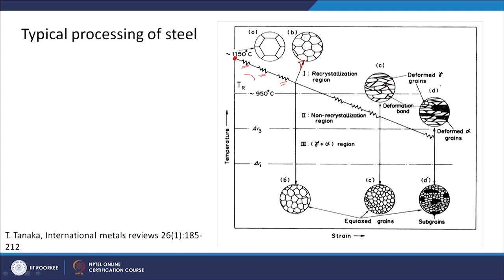deformation. So, deformation in the gamma phase, that means the austenite phase. Again the temperature is continuously dropping and then you are putting deformation here. So, these are deformed alpha grains now because you are coming into the alpha plus gamma region. So, you can see that the actual thermomechanical processing in industry is very complex. Your temperature is continuously dropping, and because temperature is continuously changing, the phase or phases in the material are also changing. So, you start with an austenite phase, then you come into a two phase region where the austenite plus ferrite phases both will be there, and then you go into the ferrite region also maybe, where only ferrite grains will be there. They have different crystal structures, and their deformation behavior will be different.